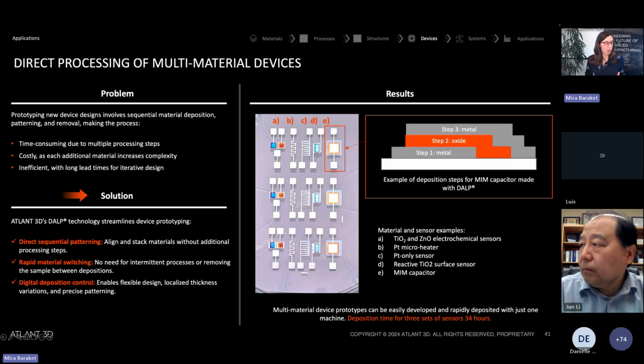So as you can see, these are all printed on the same device, and the deposition time in this case for the creation of the whole sensors was within 30 to 34 hours.